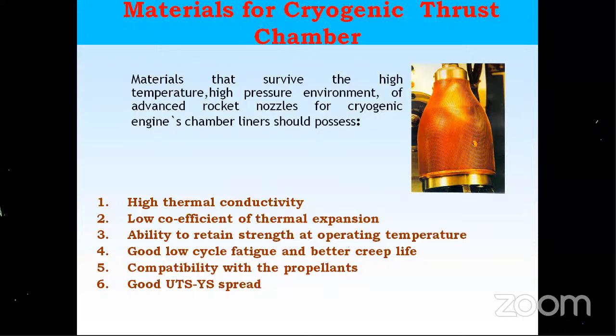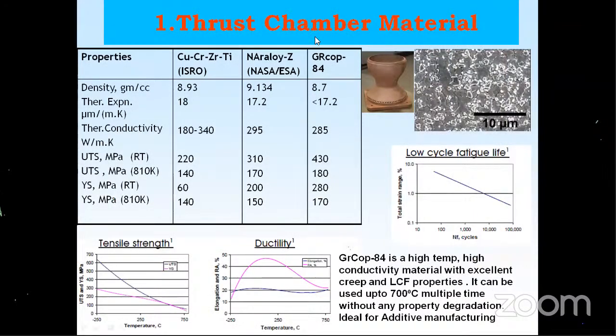Some of the material properties required for this material are high thermal conductivity. Then you will ask, can't you use nickel alloy? Nickel alloy has high strength, but the problem is conductivity is so low. It is only 10 to 12 watts per meter Kelvin, whereas copper is near 300 plus. Because of thermal conductivity, the metal doesn't melt. Also low coefficient of thermal expansion, ability to retain strength at operating temperature, low cycle fatigue strength and creep life, compatibility with the liquid propellants, especially hydrogen or kerosene or oxygen, whatever it is, and then high UTS-YS spread. That is also very important, so that even if the material yields, it doesn't cross the UTS point. Then this is the material which I have done.